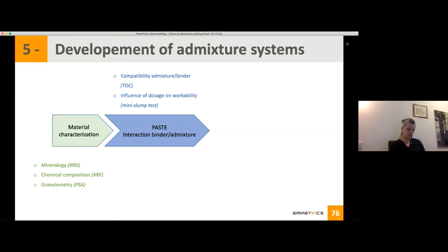What you have is that at the beginning, you will increase your dosage, but you won't have much influence over your workability until you reach a critical dosage. So you will have enough surface coverage of the cement to have a dispersing effect. Then you will see that a small difference in your dosage will have a bigger influence on your workability. So you will have something exponential. And then at a point, your admixture is all absorbed, so it won't help more with the workability. It will flatten again, or then you will have segregation.